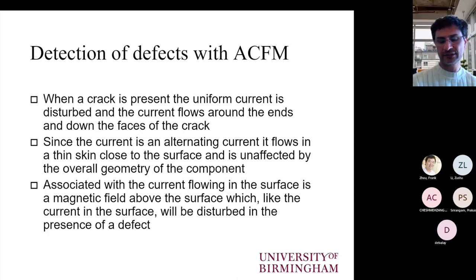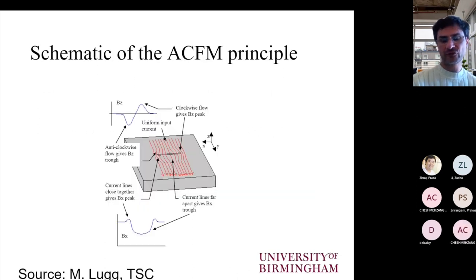And the Z orientation is the one that relates to the surface current lines that are flowing around the edge of the crack. And the BX is the one that is going below the crack, so it penetrates deeper in the material. This is the schematic diagram that shows the ACFM principle. So you can see here the corresponding BZ signal for the anti-clockwise flow and the clockwise flow around the crack edges, and the BX signal reduction for the current lines that are flowing at the bottom of the crack.